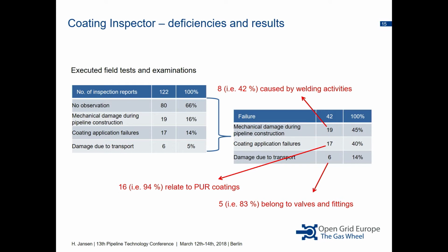And we prepared a total number of 122 reports. 80 reports were without observation, so good result. Mechanical damage during pipeline construction dealt with 19 reports, so 16% of that. Total 122. Coating application failures were found in 17 cases, and damage due to transport was in 6 cases.